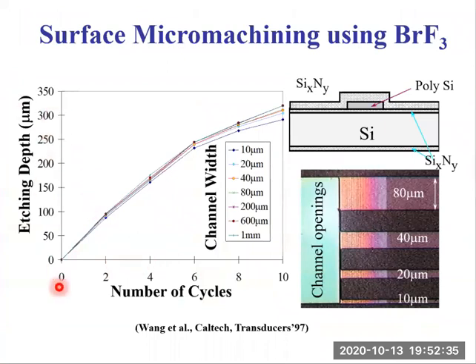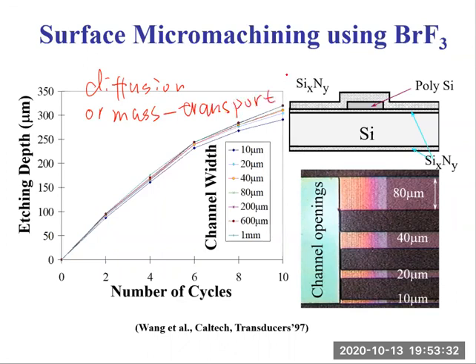This figure plots the etching depth of polysilicon inside silicon nitride channel as a function of number of etching cycles. And this horizontal axis is actually equivalent to etching time. So again, we observe these non-linear curves. So what's our conclusion? We can conclude that this bromine trifluoride etching is diffusion limited or mass transport limited, right?